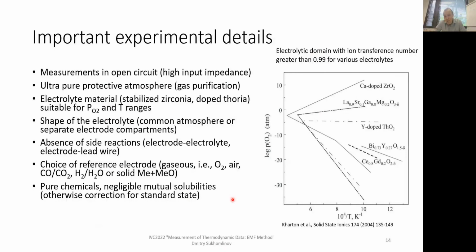Shape of electrolyte is important. I've shown you one example where a closed end tube is used. This is a pretty good arrangement. In that case, we can truly separate reference and test electrode compartments.